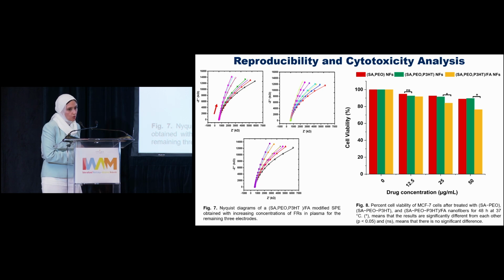We investigated also the reproducibility of our biosensor. It's a very important parameter because if any biosensor is not reproducible, it can't be applicable. We carried out the experiment under the same conditions, the same factors, with the same optimization for all the steps, and we obtained nearly the same behavior in the freshly prepared 3 electrodes, as we see. We made fitting for all the data to extract the RCT value and calculate the variation. We also obtained the same limit of detection.